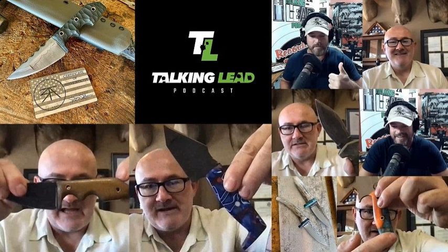So if you have a skinner versus a kukri, I use a lot of hollow grind. Hollow grind is a method that takes a lot of steel off the knife as you're grinding it. Here's an example. If you ran your finger from here to the spine, you would feel that it's concave. It goes deeper right here because I'm using the point of the wheel to grind this out. So from the blade to the center of the knife it's deeper, and then it flares back out going toward the spine, and you get basically an apple seed type edge that's shaped like this.